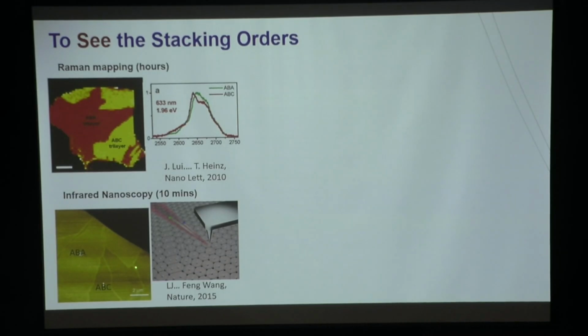Or you can do what I did, when I was still a student with Feng, we sort of borrowed this infrared SNOM technique, where we shine infrared light on a tip scanning over the graphene flake, and we collect the scattered light signal. Due to the different infrared conductivity, we can also tell the difference between ABA and ABC by scanning the tip across the flake. Okay? I was asking myself, given that there are different stacking domains inside exfoliated graphene, can I see them?